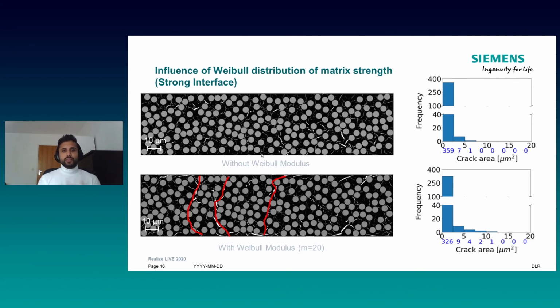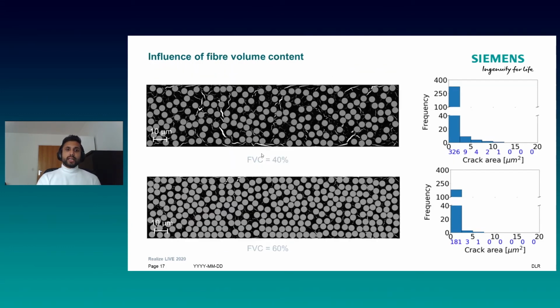And this means with this information, we can then go into other manufacturing parameters, for example, fiber volume content. Now, the images which we showed earlier were with fiber volume content of 40%. What happens if I take material with higher fiber volume content? Now, in the other case, it's 60%. And as we can see, there are almost no cracks. Or even when there are cracks, they are present within the matrix, but there are no big cracks.